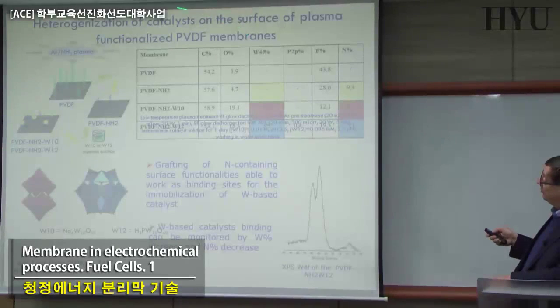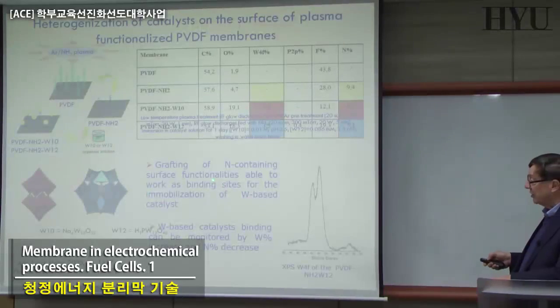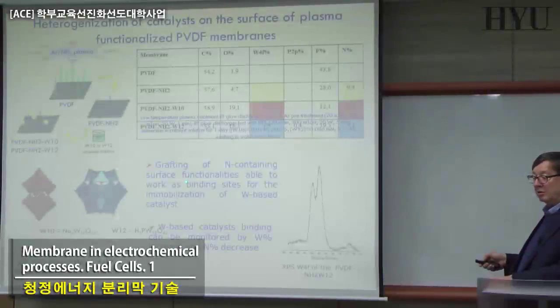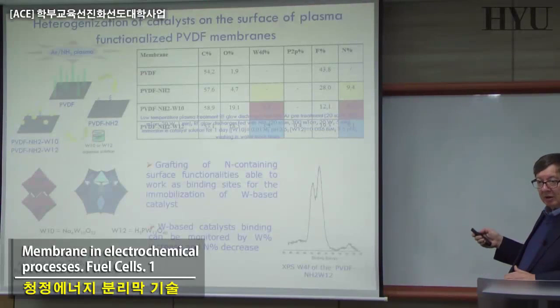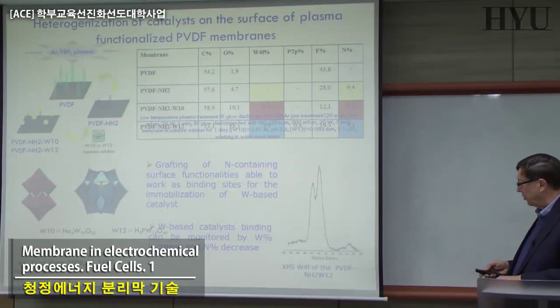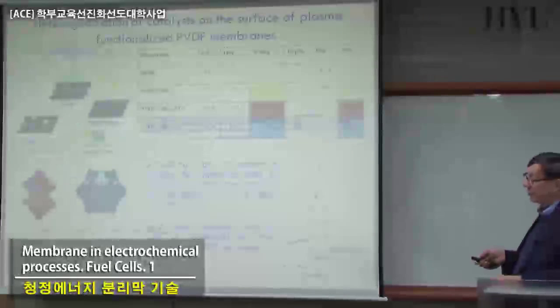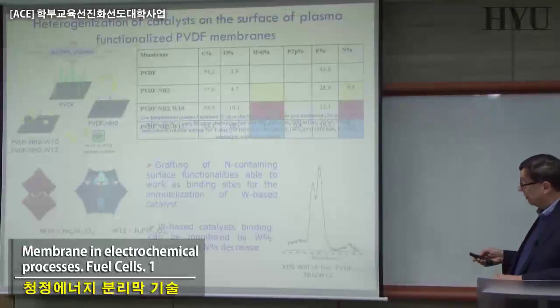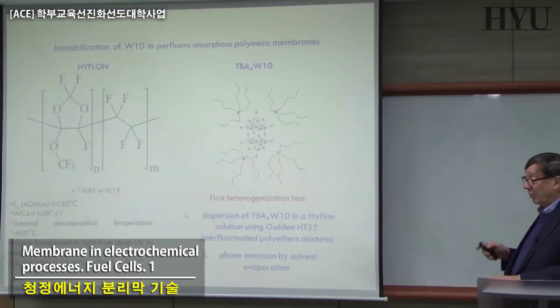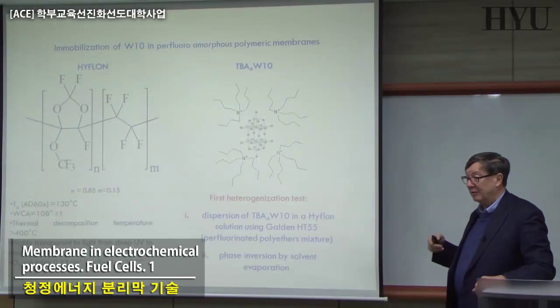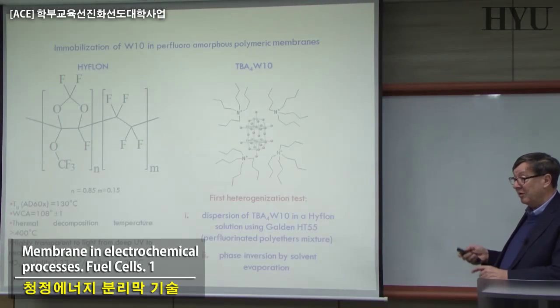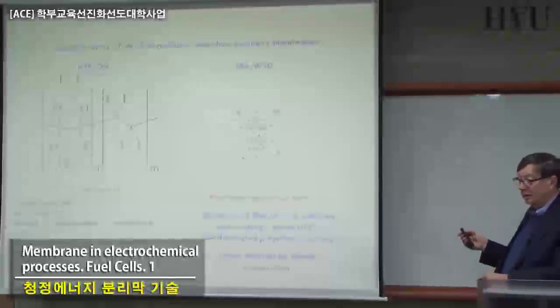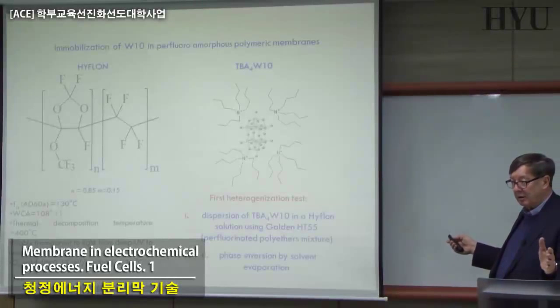Now there is also a system you can try to make with plasma-functionalized PVDF membranes. You can have a grafting of a nitrogen-containing surface, in such a way that you can have an interaction between the catalyst and the surface that you activate by a plasma system. So there are different ways of doing it, and eventually all this is trying to increase the stability in real operation, and these are systems that have to operate. It's quite interesting, one of the problems that sometimes you have, and for which you have to find a solution. And I will show you one kind of solution in this case, but this can be generalized to many other cases.